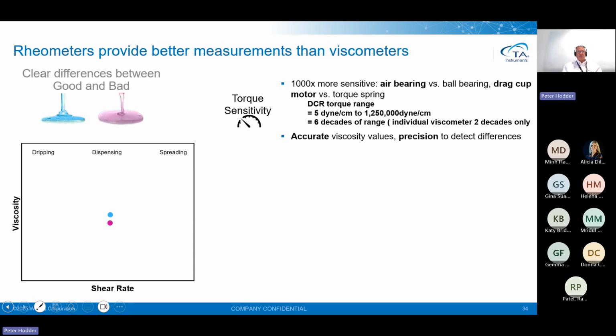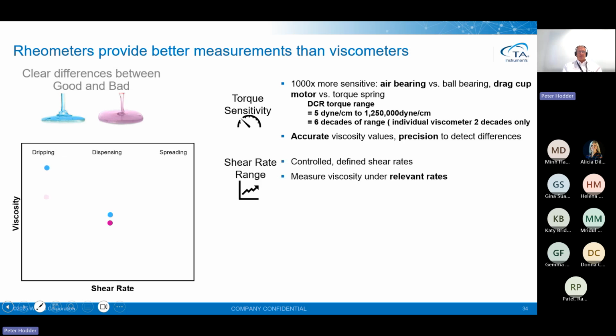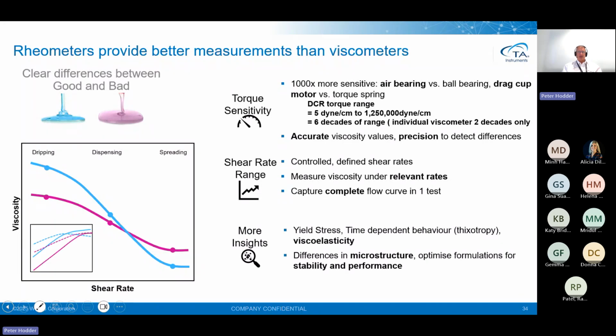We have accuracy of viscosity values and precision to detect the differences because we get confidence about reproducibility. We can apply a whole range of shear rates from low to high. So we can now simulate dripping, we can simulate spreading, and we can actually now see one complete flow curve and see the sample shear thinning. We can start to see the hints of the zero shear plateau and the high shear plateau. So we know that the system is not going to change much more than that. And we can actually do other testing. We can do yield stresses or time dependency like thixotropy, or look at viscoelasticity. And the inset there actually represents frequency data from materials to show how the sample changes on timescale.